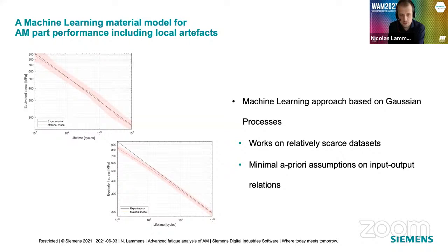The reason that we chose that is that, first of all, a Gaussian process is a statistical estimate. So it's the most likely estimate of your fatigue life. It's not going to give you a single fatigue value for a certain input condition, but it's going to give you the expected fatigue life and the standard deviation that comes along with it. And that's an important thing to know, because we have a multi-dimensional input parameter space, and it's very easy to try and predict component performance that is far outside the training data that you have available. And if you have no estimate of the standard deviation of your prediction, then you have no way of knowing how reliable your prediction is. So that was an important feature to have.